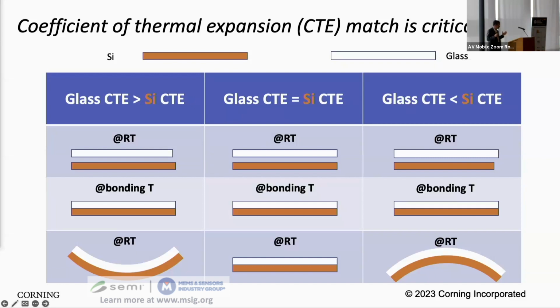And glass is beautiful because you don't have to limit the ratio of different elements like in a typical single crystal material. So by putting different materials in the glass, you can modify the CTE over a very large range. Silicon in this case is one target. If you have another semiconductor material that you want to bond to glass, we can pick another glass that has this property for bonding.